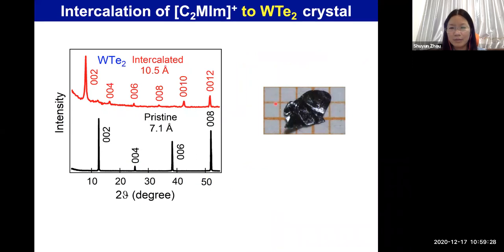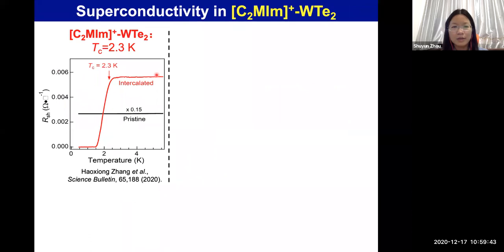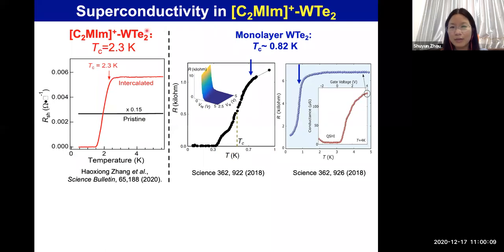So here is the sample, and the X-ray diffraction data tells us that we can completely intercalate the bulk single crystal, and we can increase the interlayer spacing to 10.5 angstrom. Now, when we measure the resistivity at low temperature, we see that this intercalation also leads to superconductivity with a transition temperature of 2.3 Kelvin here. This 2.3 Kelvin is somewhat lower compared to intercalated molybdenum ditelluride. However, compared to the monolayer tungsten ditelluride sample, the TC is only 0.82 Kelvin. So here we actually have a TC much higher than the monolayer flake.